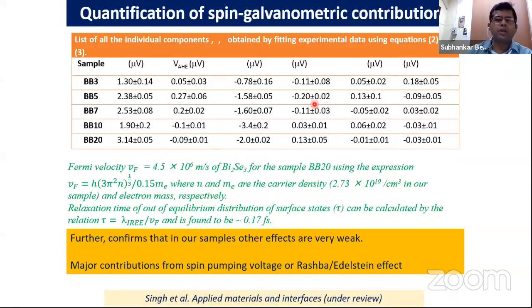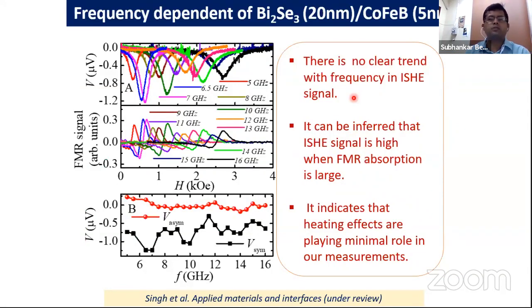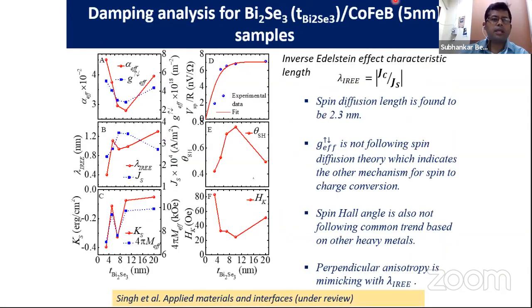Then we evaluated for different samples how much this voltage is, and I think this plot is more informative, where you plot the effective damping constant as a function of bismuth selenide thickness, then the spin Hall angle as a function of thickness. I think this plot is very useful, this spin Hall angle, which shows that there is not a very linear trend. Usually, if you observe the spin Hall effect, mostly the theta SH should decrease continuously as a function of thickness. But here you have an increase and decrease that shows that it's not really from the bulk, it is rather from the surface.